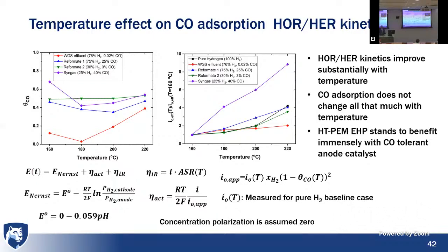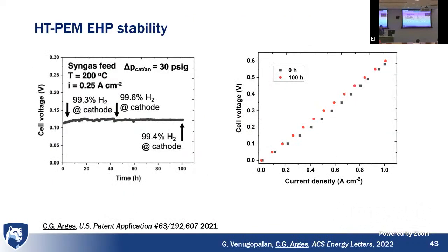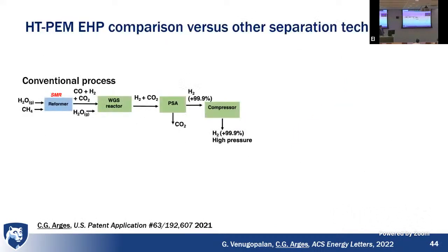So this is an active area that we're still trying to work with a little bit, trying to understand what happens when you go to high temperature, different catalyst materials. Is it the contaminant poisoning of the catalyst, or is it improved kinetics for the reaction you're trying to do? The system is stable for over 100 hours for purifying hydrogen from syngas. So I won't elaborate on that.